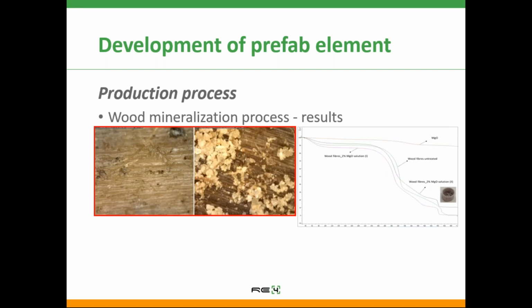In the figures, the red rectangle on the left shows representative wood fibers soaked in water before and after the mineralization treatment. The observed treated fibers are covered by mineral parts. On the right, the thermographs detected by Mettler Toledo equipment for 4 different samples are reported. An interesting result can be observed at about 500 Celsius degrees, where no residuals are observed for untreated wood fiber, while a residual of approximately 10% of mass with respect to the initial treated wood mass is observed.